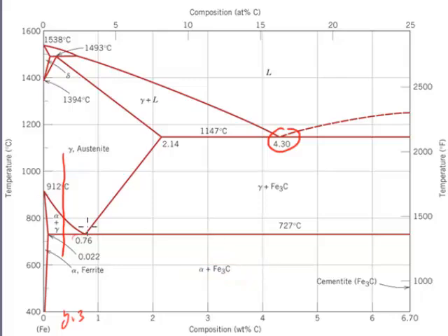That eutectoid point is right here at 0.76 weight percent carbon. Now that temperature, 727 degrees C, remains important all the way across.